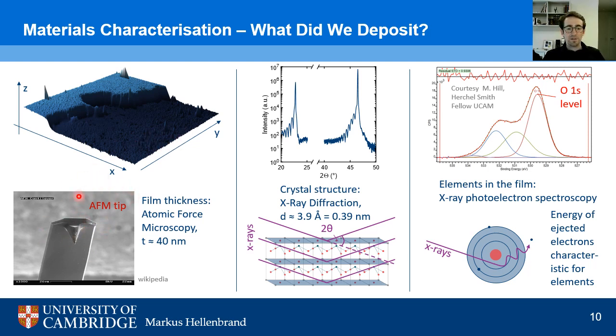Now, in this technique, atomic force microscopy, this very sharp tip, which you see here in the micrograph, scans across the surface, and then a laser is directed to be reflected from the top of this tip. So the laser comes in from one side, is reflected from the top, and then measured in a detector over here. So if we have a large surface roughness now, or if we encounter a step such as this one, it means that the tip will move up or down, and consequently the reflection of the laser will be detected in a different place. So from the reflection of the laser, we can calculate the height that the tip encounters